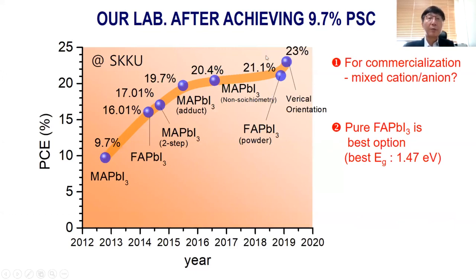In our lab, after achieving 9.7% perovskite solar cell of the solid state version, we have focused on the pure perovskite having the methyl ammonium in the A site or the formamidinium in the A site, because we would like to focus on the phase pure composition instead of the mixed composition. The mixed composition may undergo phase transition, which may not be suitable for commercialization. And also, FAPbI3 is the best option because the band gap is more appropriate to the Shockley-Queisser limit.